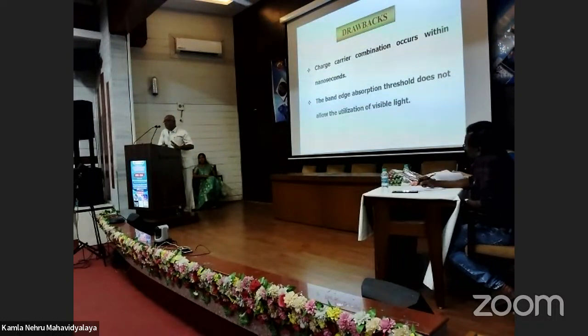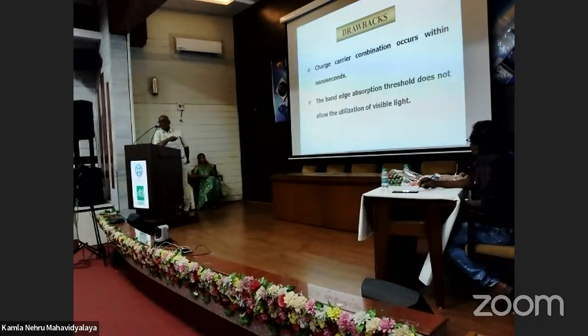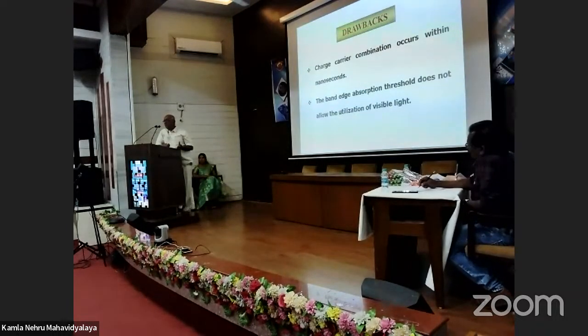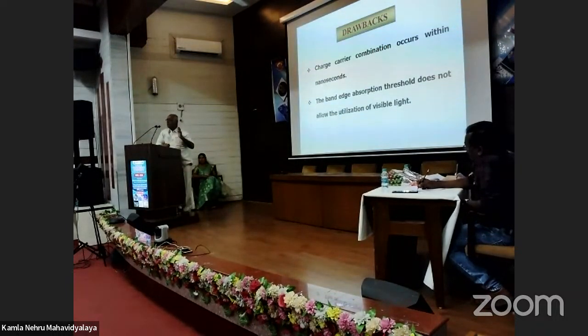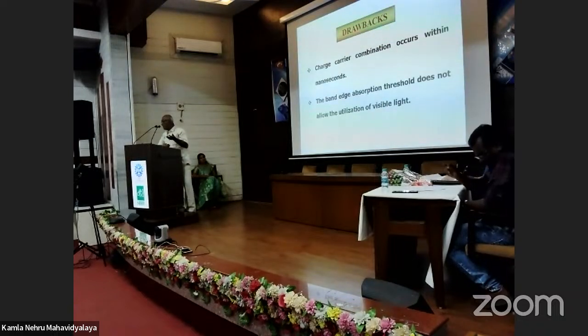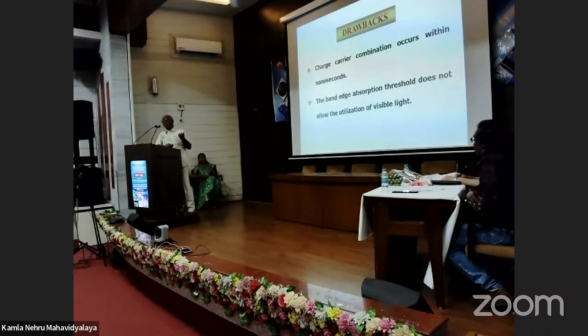And what is the drawback? Simple TiO2 cannot be used effectively because electron-hole recombination takes place. Another one is that you have to use only UV light. Charge carrier recombination occurs within a nanosecond, and the band gap absorption threshold does not allow utilization of visible light. So we have to modify the TiO2. Once you make the TiO2 solar active, or take zinc oxide or silicon oxide, which are active in the UV region, you can make them active in the solar or visible light region by modifications.